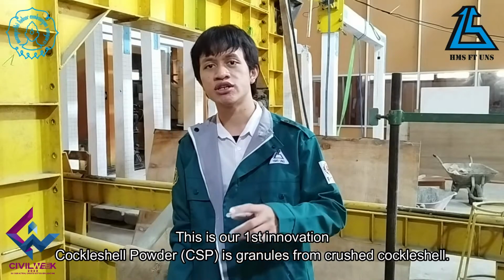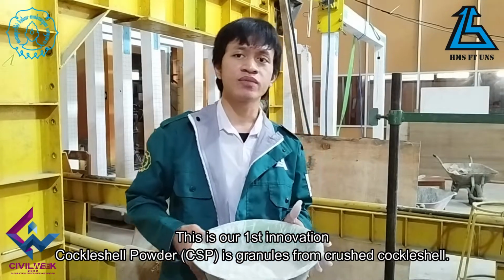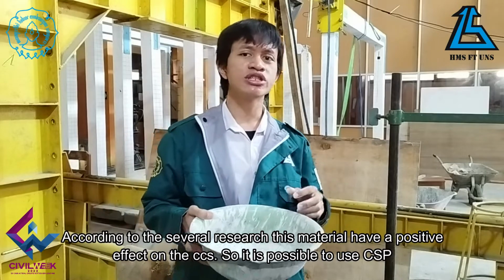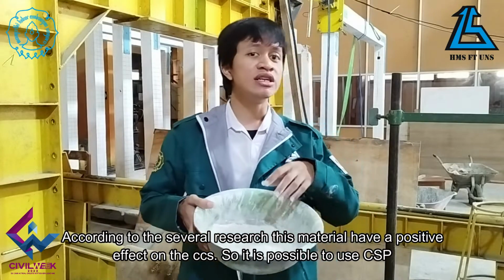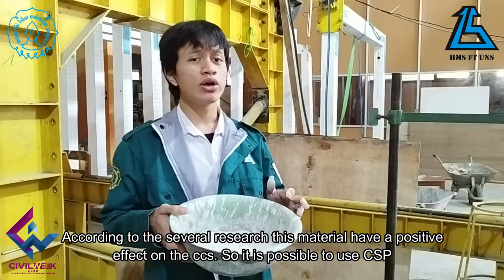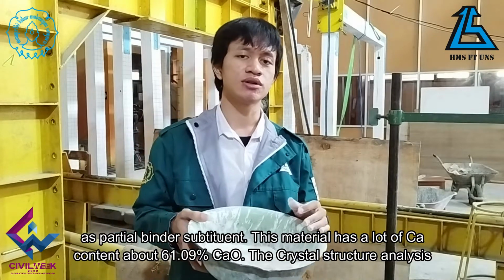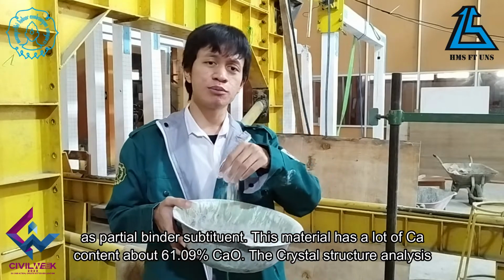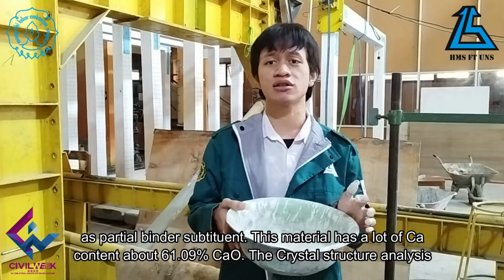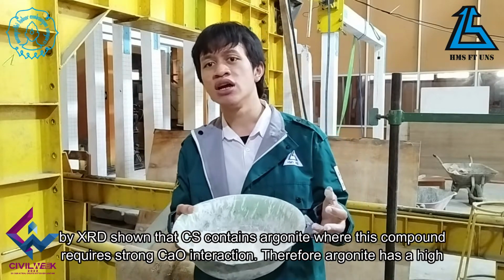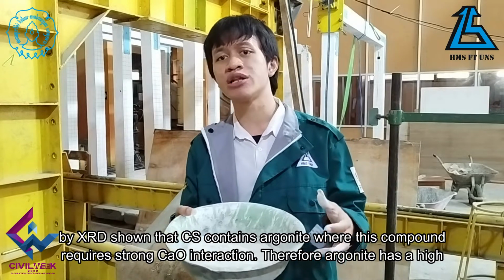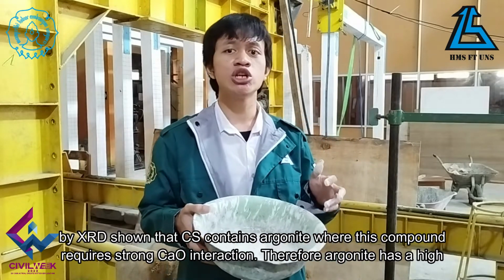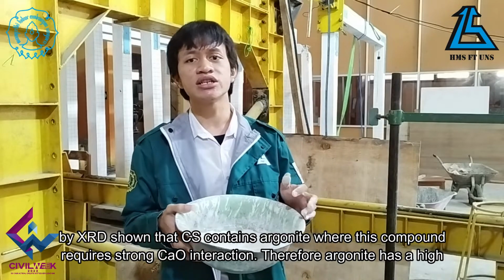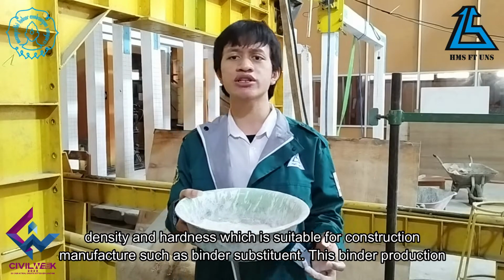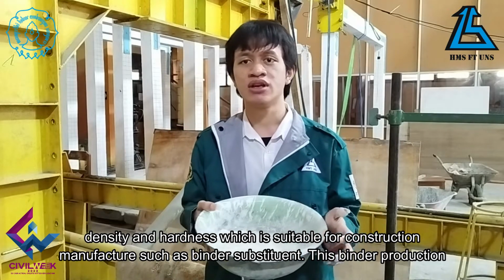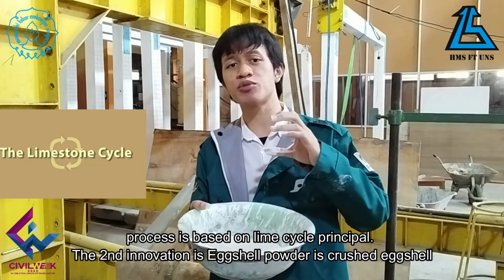This is our first innovation. Cockle shell powder or CSP is granules from crushed cockle shell. According to several research, this material has a positive effect on the concrete compressive strength. So, it is possible to use CSP as partial binder substitute. This material has a lot of calcium content, about 61.09% of calcium oxide. The crystal structure analysis by XRD showed that CS contains aragonite, one of the calcium carbonate polymorphs, where these compounds require strong calcium oxide interaction. Therefore, aragonite has a high density and hardness, which is suitable for construction manufacture, such as binder substituent. This binder production process is based on the lime cycle principle.